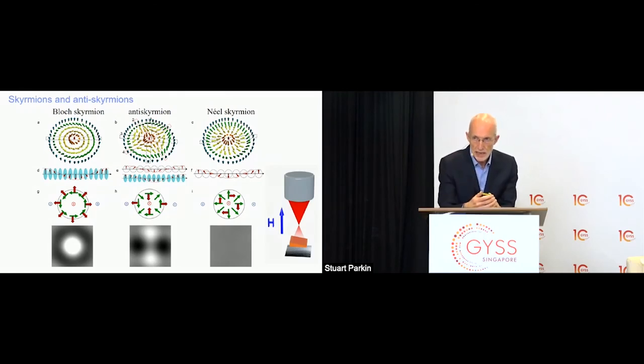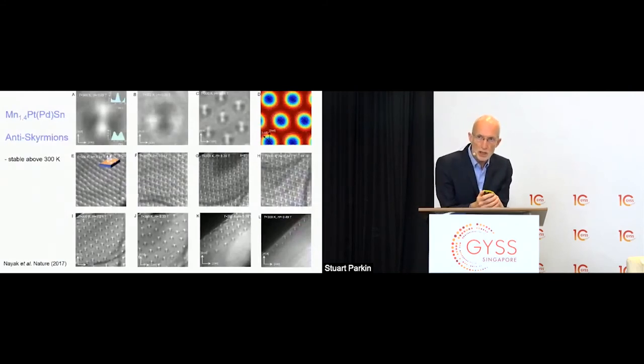On the other hand, the anti-skyrmion we calculated should show an image in the Lorentz microscope of these two white dots of increased intensity and two black dots of decreased electron intensity. And we saw this, and I hope you can see in the top column to the left in part A, you can see such an object. This is obtained by passing a very high energy electron beam through an ultra thin lamella and detecting the electrons that are subject to the Lorentz forces in that lamella.